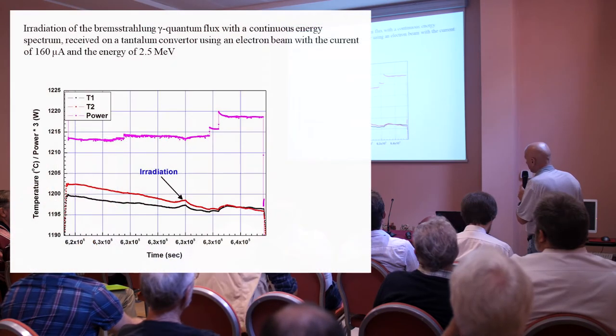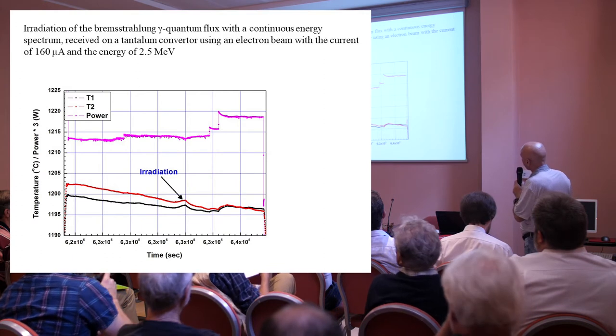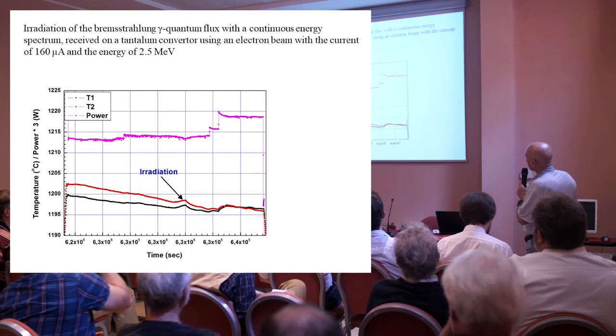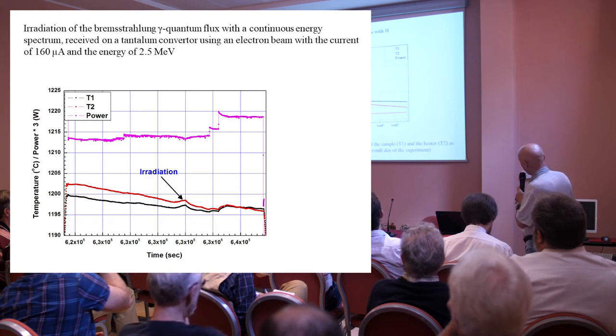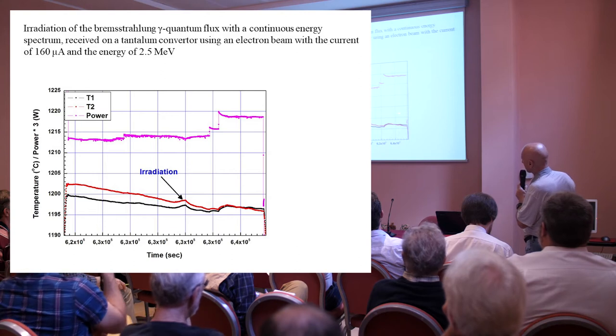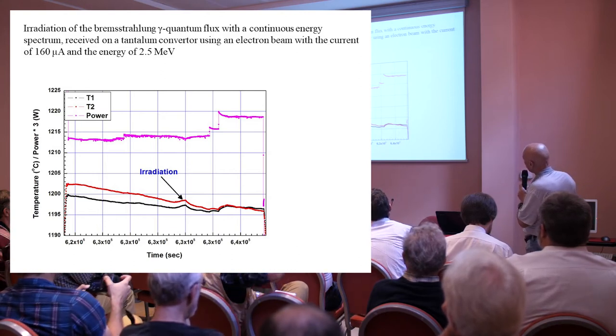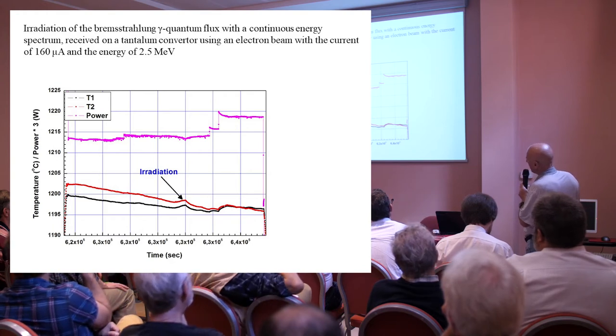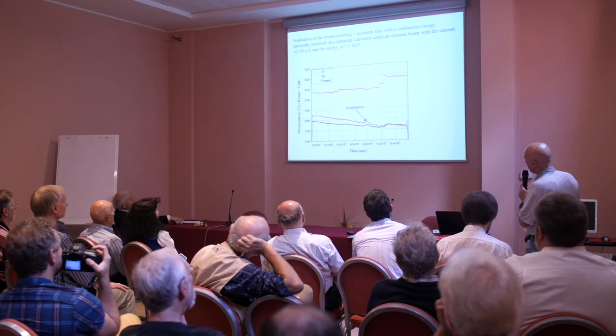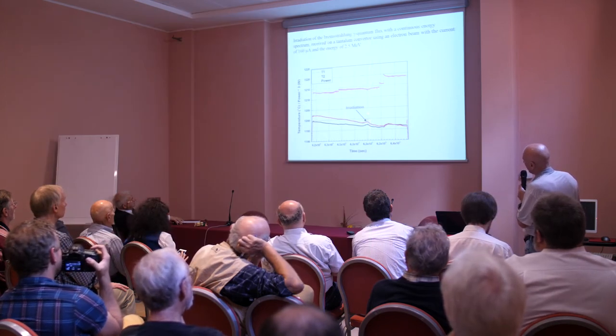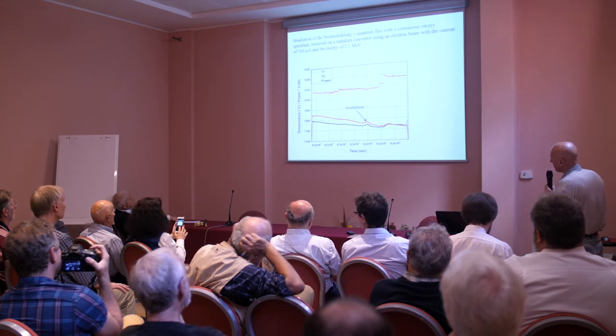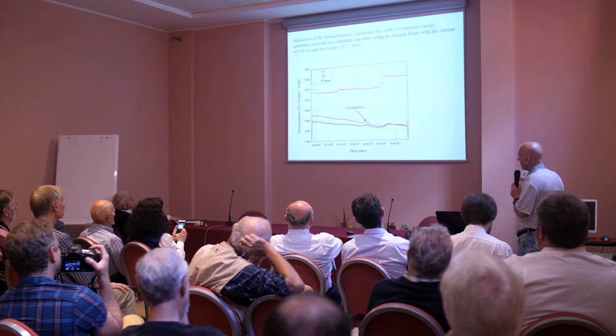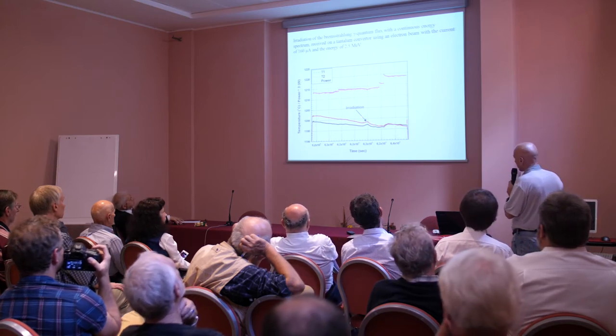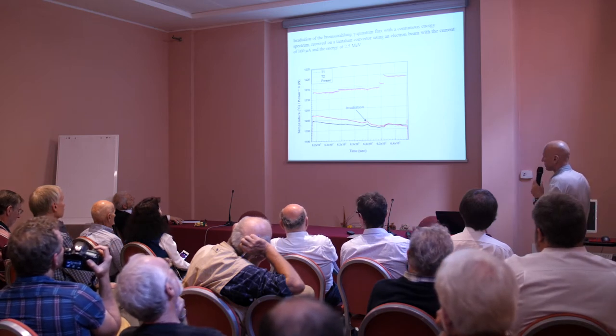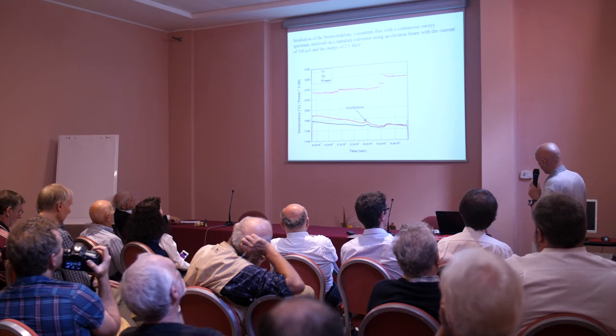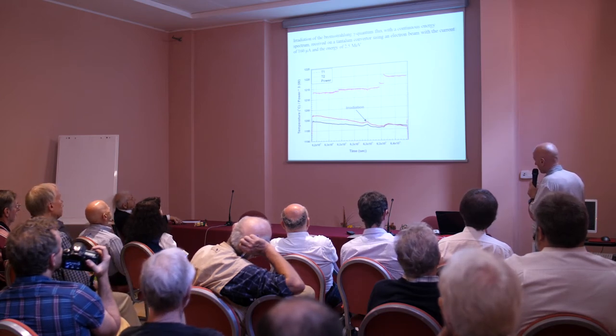And then in another try, a few words about this experiment, at this stage we also tried to apply this gamma irradiation. But as you can see, it resulted only in small heating peaks, but it didn't change the order of the temperatures. So it means that both fuel and the heater were slightly heated by the gammas. So we didn't expect much, actually, at this range of temperatures, for some reasons that I probably will tell you on Thursday when I explain our theoretical background.